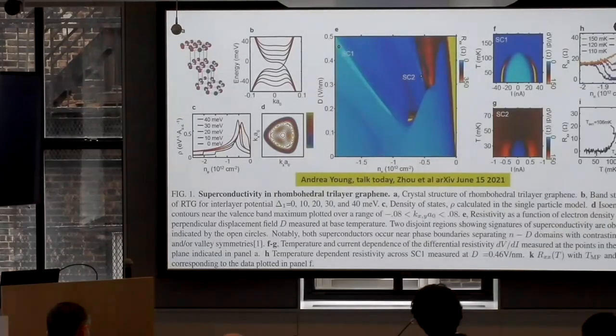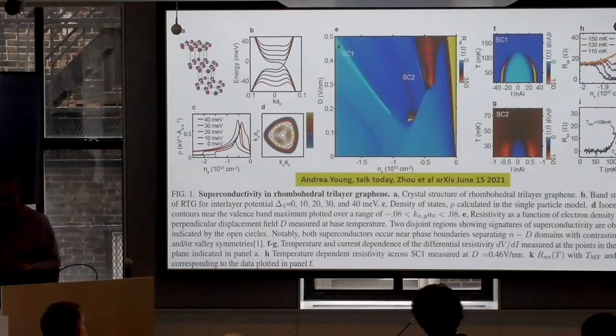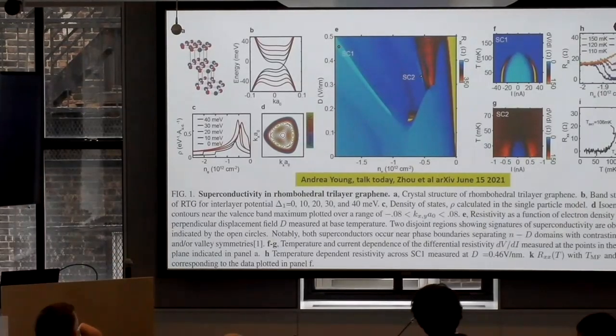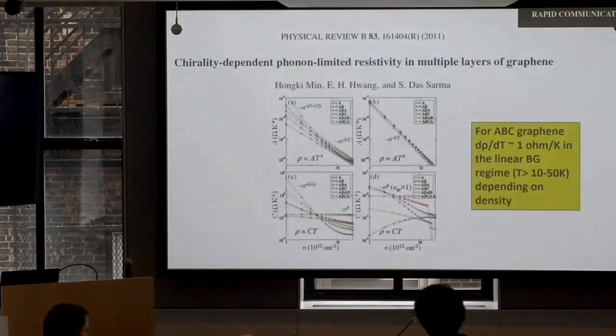So the question immediately comes up. Our competitors, who wanted it to be electron-electron interaction, like Erez Berg and Mike Zaletel, two very, very smart guys, wrote a paper where they said, in our theory, they don't see linear resistivity in temperature. But the problem is Andrea only went up to 20 Kelvin. We have now done this theory very carefully, and resistivity should be linear around 50 Kelvin. It's a very big question, seeing linear resistivity with the correct slope that our electron-phonon coupling gives. So that is an open question, and he has promised to do the experiment.